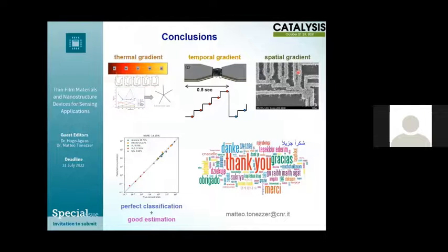We were able to make one metal oxide, one chemoresistor, one gas sensor based on metal oxide nanowires, having perfect classification, because in all the cases it had 100% correct classification. It was identifying the gas perfectly, and also giving a very good estimate of its gas concentration.